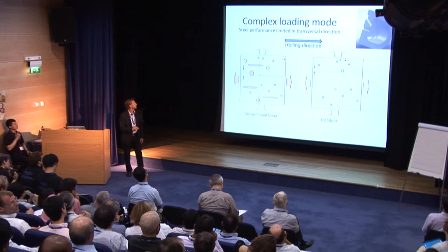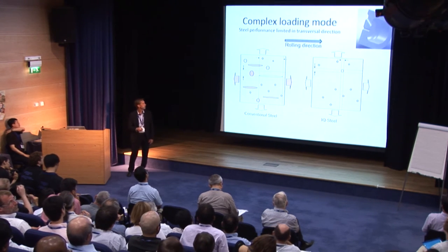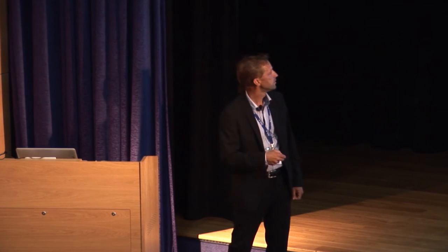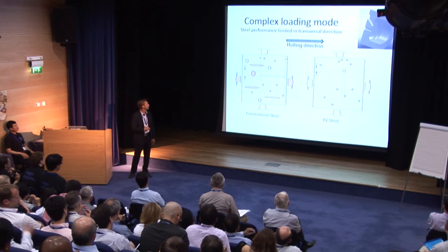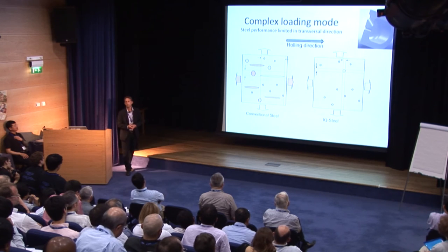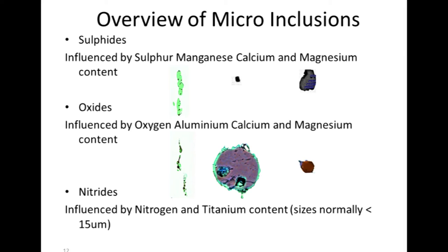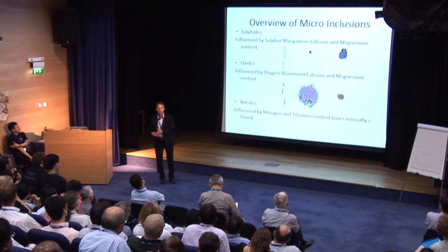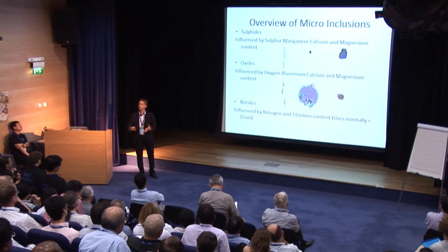That's why we are trying to get away from conventional steel and developing more and more steels that are cleaner, with less elongated and smaller inclusion sizes. These are typically sulfides deformed in the rolling direction, and the round ones more representing the oxides. If we can make those into another shape, they will be more symmetrical. And that's possible. Going from being a physical metallurgist, we also need to talk to the process metallurgist, because they also need to be fed with this kind of information, what is really important for them.